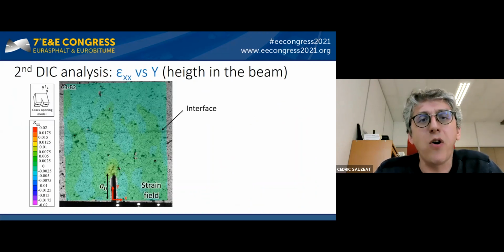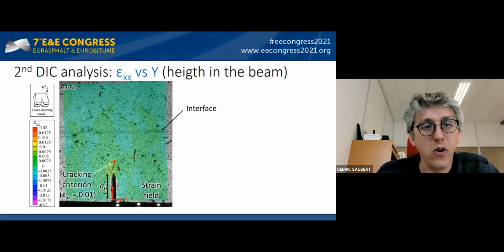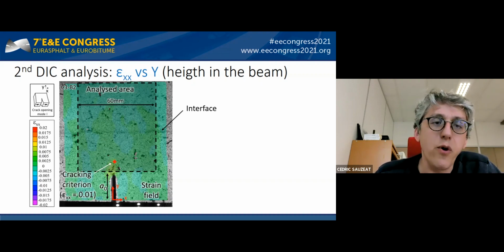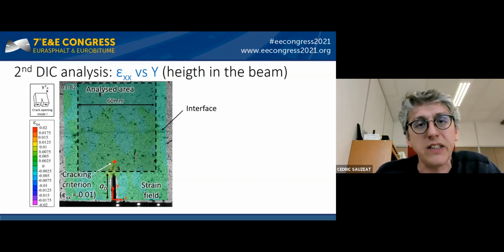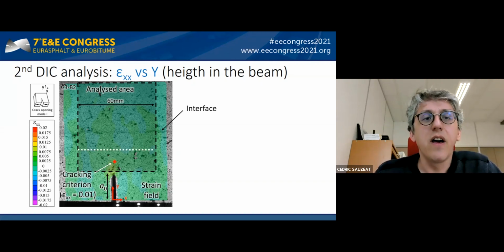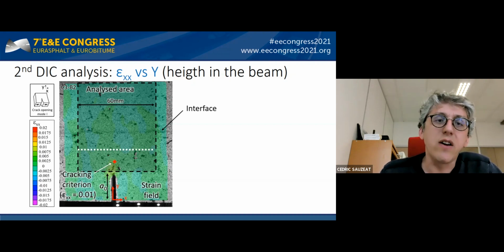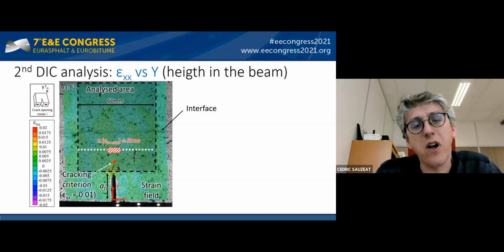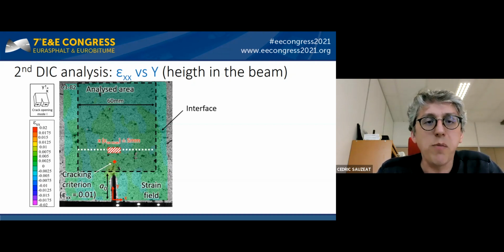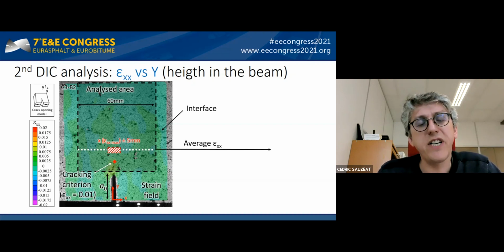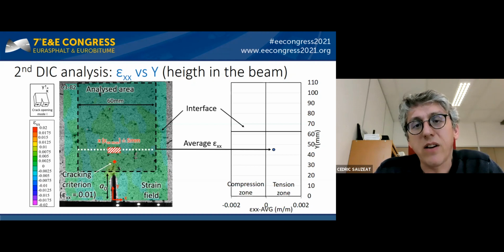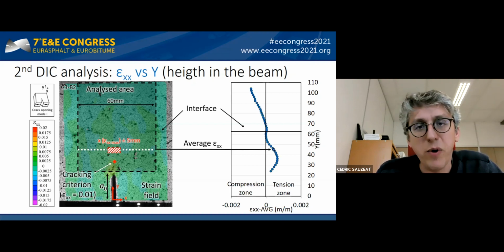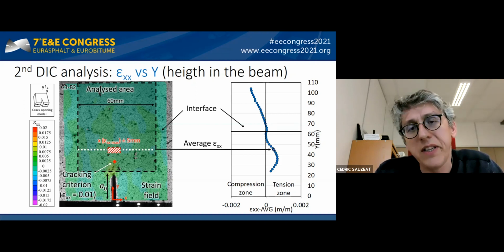The second analysis that we perform is to obtain the strain in function of the height of the specimen. So you have here the height obtained from the crack criterion from the first analysis. And we analyze a restricted area around the center of the beam. For each line, we just get an average value of the strain in the central part. With this average value, we can obtain for each line a value of strain. And if we perform this for all the lines in the height of the specimen, we have the evolution of the strain in the height of the specimen.